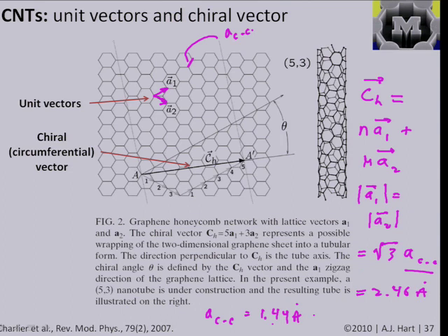Yeah, so the periodic table, which we'll see at the end, has a nice summary of all these things. The a_CC is 1.42 in graphite and about 1.44 in a carbon nanotube, because you have this surface effect, because you have the stress necessary to wrap it up when you create a tube. The bond distance actually depends on the diameter of the tube slightly, and we'll see that later in terms of mechanical properties, but it's just like we saw for gold.